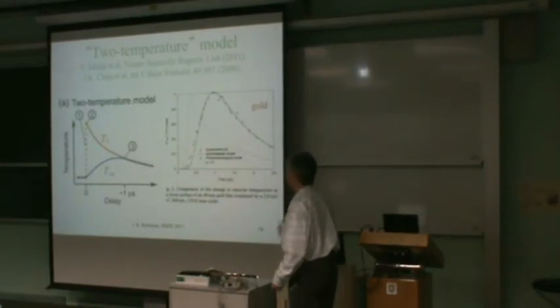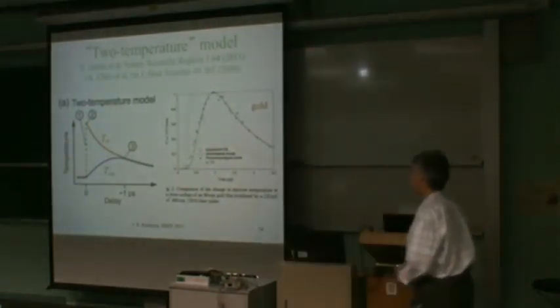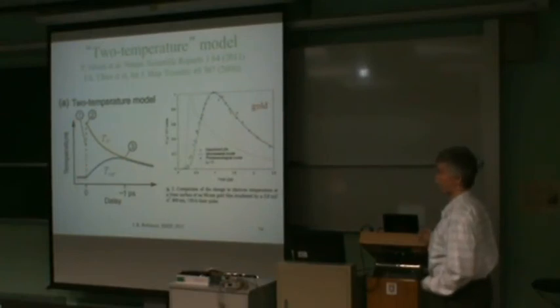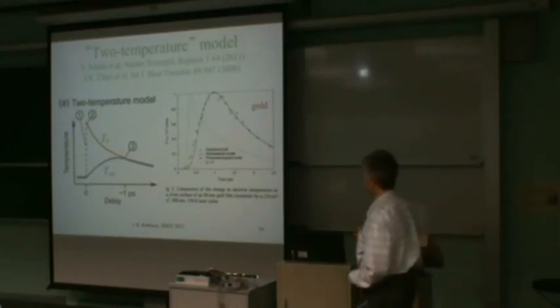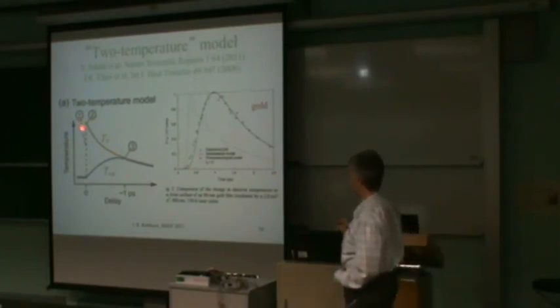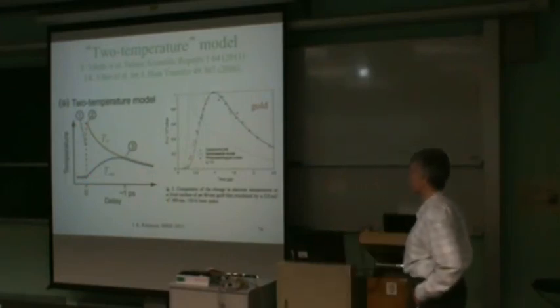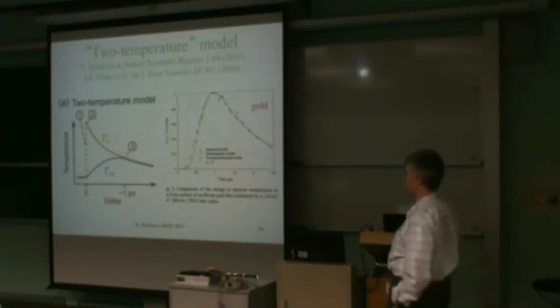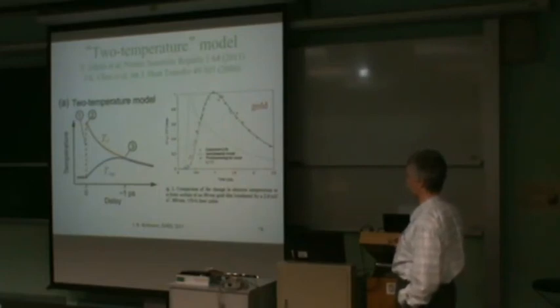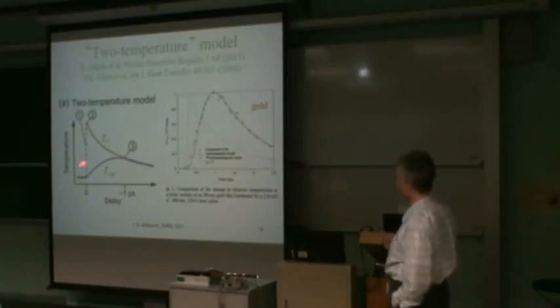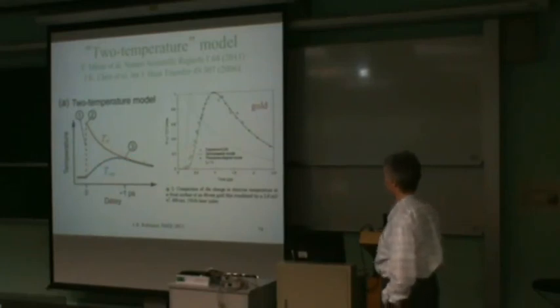And the correct interpretation of what's going on is that when you laser excite a metal, you first of all excite the electrons, but you don't see the electrons in an X-ray diffraction experiment. What you see is the lattice, and there is a time delay between the excitation of the electrons and the coupling to the positions of the atoms inside the crystal, which is given by an electron-phonon coupling constant of some kind.